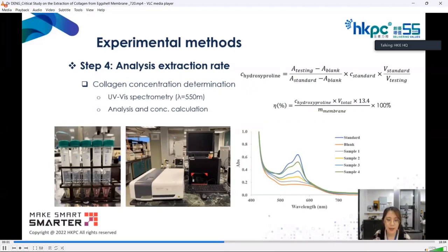To determine the hydroxyproline concentration, the UV-VIS spectrophotometry method was used. This method is based on the oxidation reaction between hydroxyproline and chloramine-T, since the oxidation product can react with dimethylaminobenzaldehyde to form a compound with a characteristic absorption peak at 550 nanometers. The concentration of hydroxyproline can be determined by measuring the peak intensity by UV-VIS spectrophotometry. The intensity of color was measured in a 1 centimeter glass cell at a wavelength of 550 nanometers.